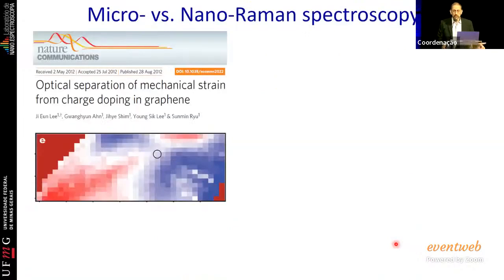Okay, so what is the achievement that you get with the nano optics? This is one very famous paper in this area, where this is a piece of graphene, and what the authors, these Korean people, did, they colorized the graphene. Every pixel here is one Raman spectrum that was taken from a specific location in this graphene, and the color here renders the frequency of the Raman peak. And the frequency of the Raman peak, the authors showed, is related to either strain or doping in the material. And with strain and doping, you change many properties of the material, okay?